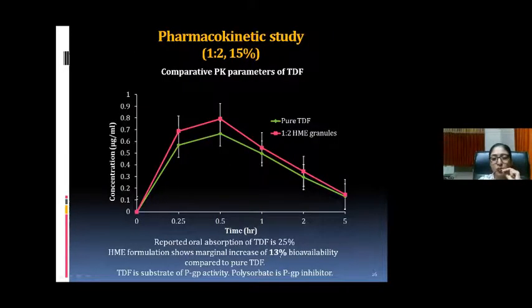Similarly, pharmacokinetic studies were carried out for the 1:2 ratio, 15%, and the reported oral absorption of TDF is 25%. Here we can see that the HME formulation shows a marginal increase of 13% in bioavailability as compared to the pure TDF. Also, TDF is a substrate of PGP activity, so we are adding polysorbate, which acts as a PGP inhibitor and tries to increase the bioavailability of this drug.